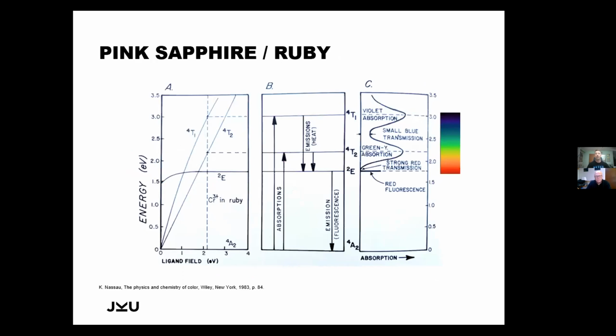So this might look a little bit weird, but it's a wonderful explanation given by Kurt Nassau in his book, The Physics and Chemistry of Color. And it helps us to explain wonderfully why we have the absorptions in pink sapphire or ruby that we see. We have here a so-called term diagram where we have the ligand field, which is just a measure of the symmetry or the shape or the distortion of the crystal field of the oxygen atoms, or oxygen ions to be precise. And we have the different energy levels that the chromium has.